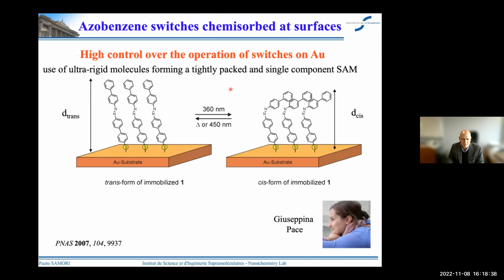So our activity started nearly 20 years ago, in 2003, when I started my independent laboratory. And then the first paper we came up with was in 2007. The idea there was to play with a highly rigid self-assembled monolayer made of a rigid molecule, an azobenzene, that was synthesized by Professor Marcel Mayor in Basel. And this azobenzene has a biphenyl on the two sides of the azo group. And it tightly packed like arene thiols on the basal plane of gold, thanks to the presence of this sulfur unit here. And it formed a chemisorbed self-assembled monolayer,